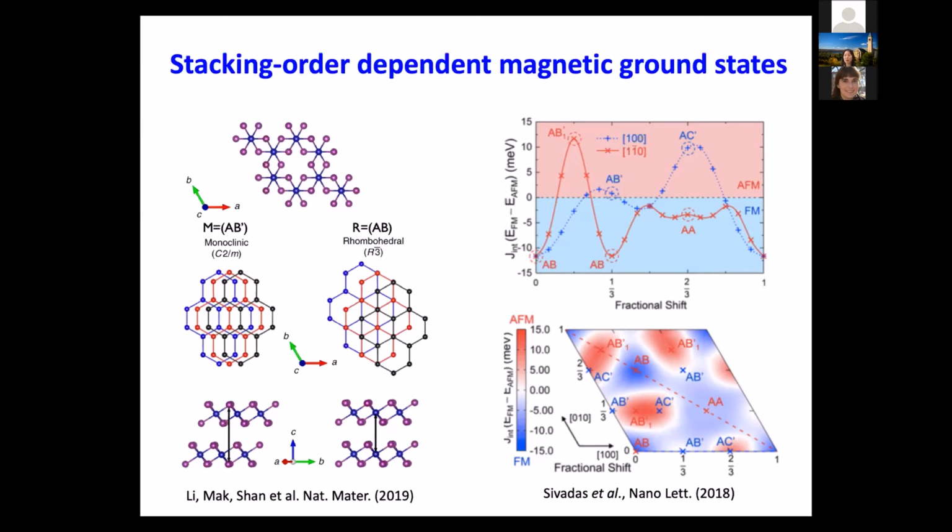And that could explain why we observe antiferromagnetic interaction when we get down to two layer. So likely that the stacking order is trapped once you cool down to low temperature. You stay at the monoclinic, which is favored at room temperature. And this is the preferred magnetic interaction.